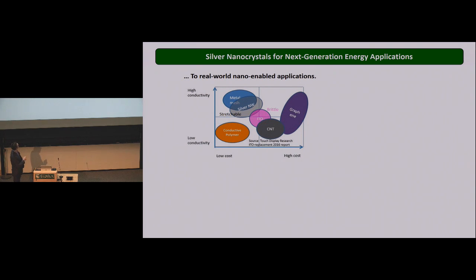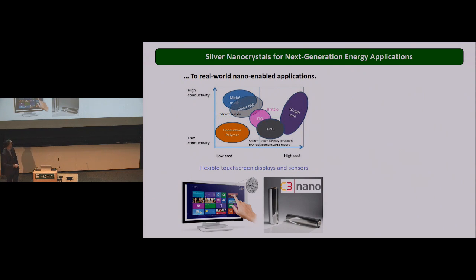These materials can be very stretchable, as opposed to these ITO displays, for instance, that are extremely brittle. So application of the silver nanowire network films is, for instance, for sensors or touchscreen displays. So you can imagine that the touchscreen of your smartphone could now be produced with this technology on a much larger scale. So imagine, for instance, large screens that would be touchscreen displays, okay? And what has been enabled here is because now we can deform this film of wires easily, as opposed to ITO. We can use processes like rolling to produce larger displays, okay? So for instance, this company in California, C3 Nano, makes large displays already out of silver nanowires.